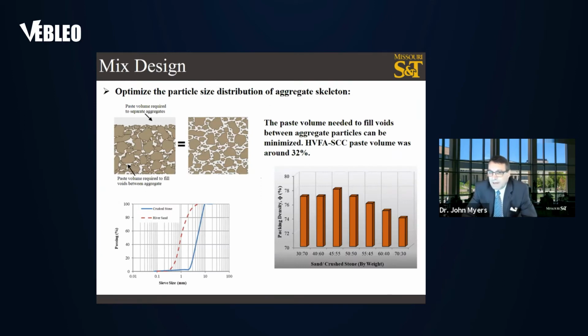Phase 2 included optimizing the particle size distribution of the aggregate skeleton. Fine to coarse aggregate ratios were investigated to optimize the particle size distribution of the aggregates. So in other words, if we can minimize the void space and densely pack the concrete based on the particle size, we can minimize the use of water and thereby help reduce the amount of shrinkage and creep in the mix design and optimize it.